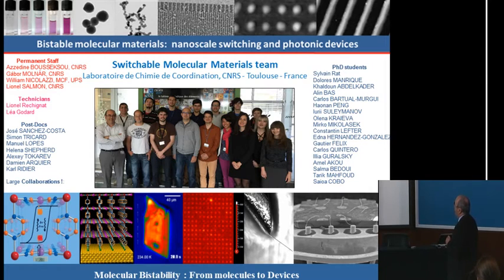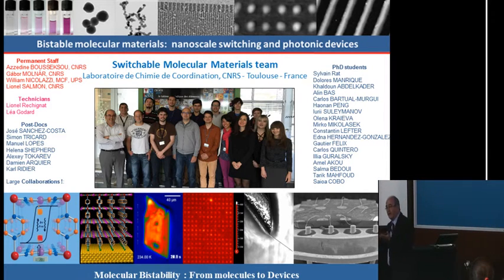And then we want also to make thin films. So then we want to fix this molecule into surfaces. And the question for chemistry is that you want to fix the molecule on the surface, and then you want to maintain their properties. Because you know, when you try to fix a molecule on a surface, you have many interactions with the surface. When you have a balanced situation where you have a tiny equilibrium between two spin states, which is quite fragile, generally you lose the property of the bulk. And then the question is to make thin films.